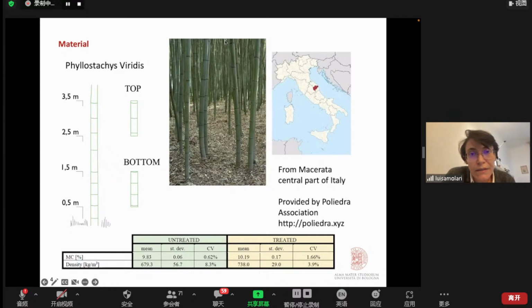And so we took these culms, and we took two parts of the culm, a bottom part from 0.5 to 1.5 meters, and then a top part from 2.5 meters to 3.5 meters. And we performed some tests on these two parts of the culm, treated and untreated.